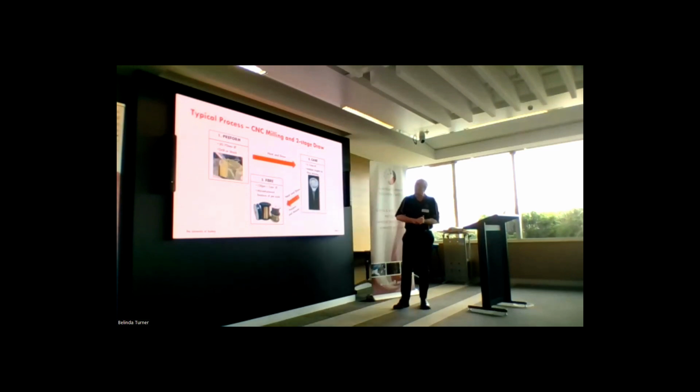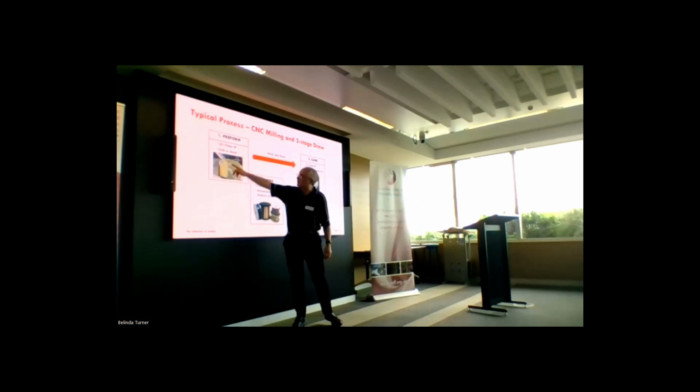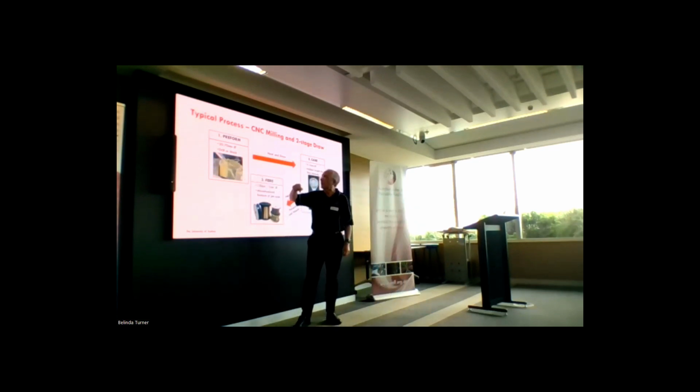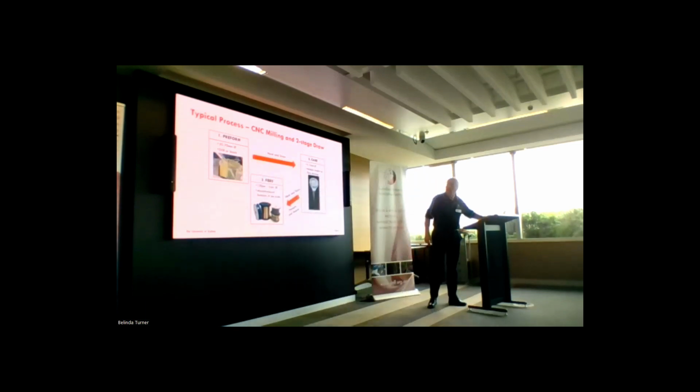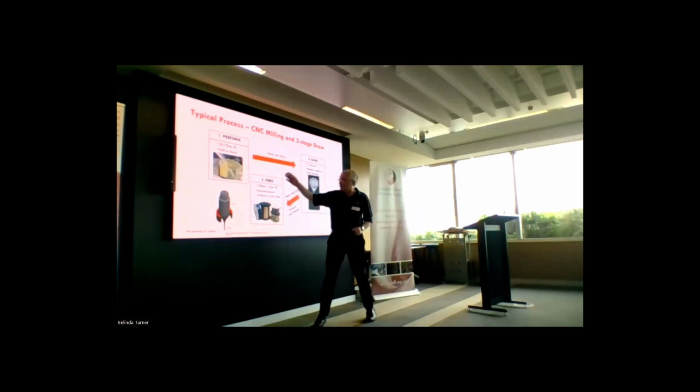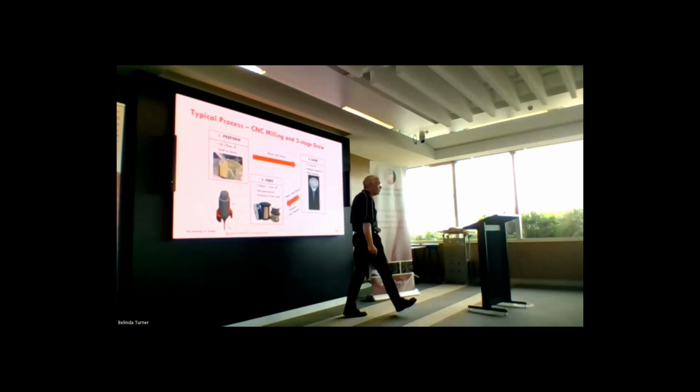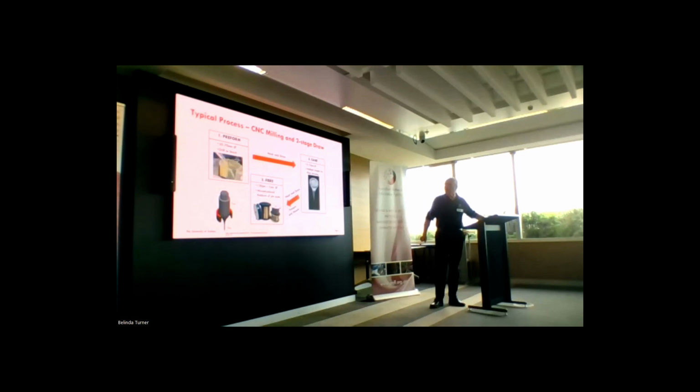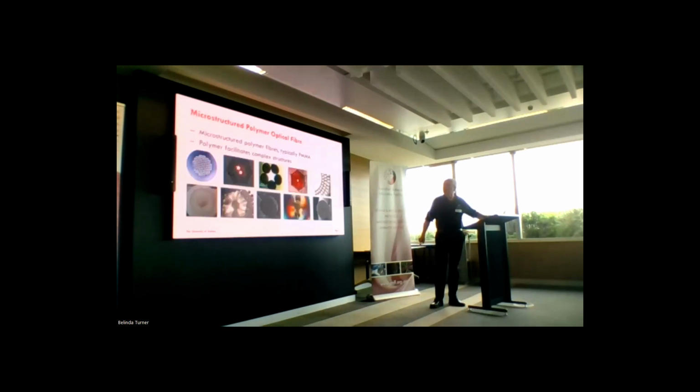The important thing is how you create the pattern in here. This is showing us using a CNC mill, drilling a whole series of holes. We can also use stacking, 3D printing. Historically, we did a lot of work with drilling. These days, typically, we'll use a stack and draw process, which was described in one of the earlier talks.